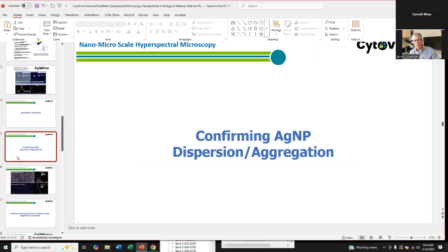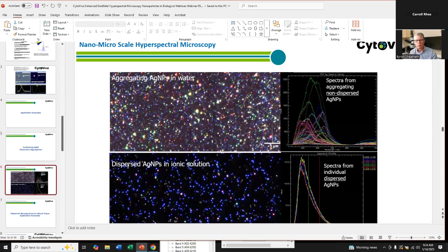The first application that we're going to focus on is confirming silver nanoparticle dispersion and aggregation. This was a group that was developing ionic solutions that will allow these nanoparticles to remain nicely dispersed in this media over long periods of time relative to a wide range of applications. And so if we capture an image of these silver nanoparticles, which were originally 30 nanometers based on manufacturers' measurements of these, we see that when they're in water, we visualize lots of aggregation. Silver nanoparticles in the 30 nanometer size, when they're truly dispersed, produce a reflectance spectrum in the 450 nanometer range. And so they are blue in nature.